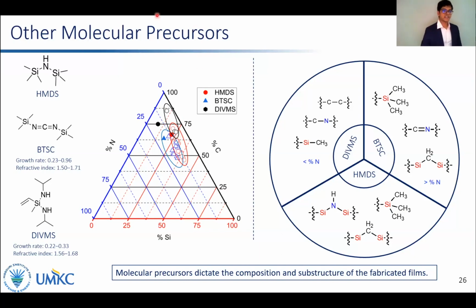A preliminary analysis of the FTIR reveals that the BTSC derived films contain carbon double bond nitrogen moieties along with terminal methyls and methylene bridged carbons, compared to HMDS. One thing we observed was that it incorporated a greater percentage of nitrogen in the films compared to HMDS, probably due to nitrogen existing in strong carbon double bonds in the precursor.